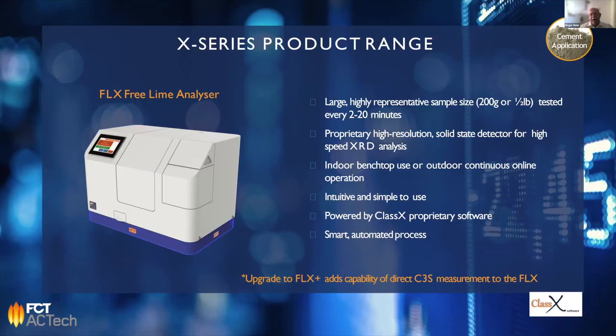In the next step, more or less, we switch from the XRF to the XRD part. This is the free lime analyzer, which is usually positioned after the clinker crusher, after the sintering process, to see the free lime as an indication of the burning conditions in the kiln. And this analyzer uses only the XRD technology.